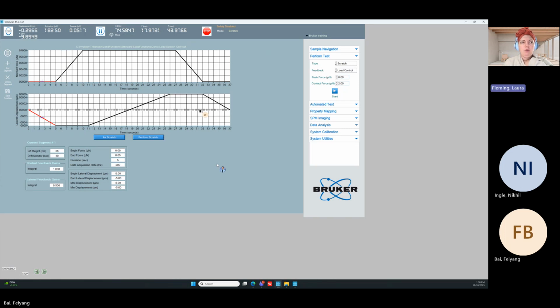For the normal direction, you technically get a choice. You could do displacement control, but I encourage you very much not to. The reason is that people think that the displacement of the tip into the sample will also be constant, and that's not necessarily the case. This is a little tricky, but we have to think about physically what's happening. When we displace the tip, what's really displacing is that center plate of the transducer. So the measurement is inside the transducer. It says move 2 microns, so it moves 2 microns inside the transducer. That means during indentation it's going to be the same thing, right? Because you touch the sample surface, then you go 2 microns into it.